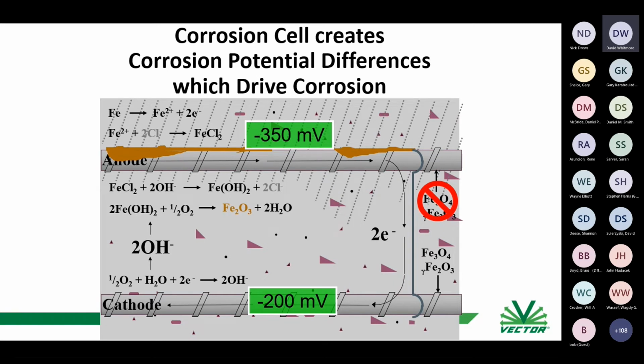But the point that I want you to walk away with is that there's a difference in voltage between here and here. And the reason that exists, the reason this potential is more negative, is because of this reaction here at the top. The iron is dissolving and generating electrons. The electrons, by definition, are negatively charged. They will shift the potential to be more negative, okay? Because they're negative, the electrons want to flow to something that's more positive. So they're going to flow to anywhere that is more positive to where they're being produced, okay?